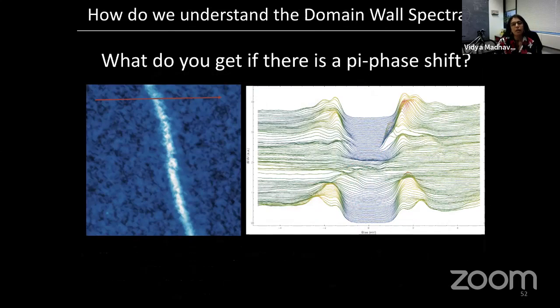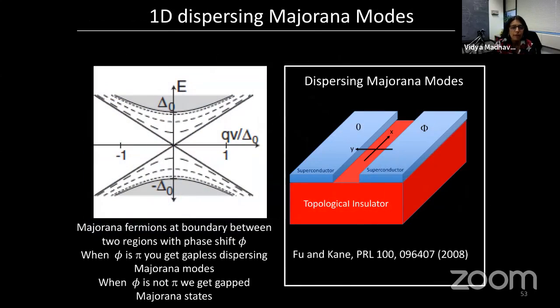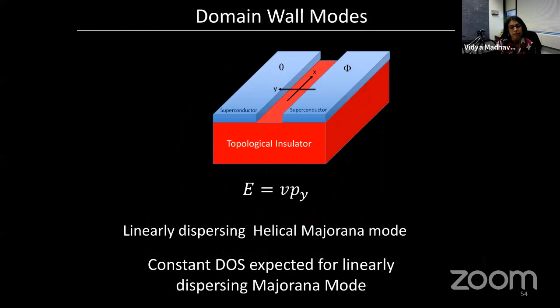To answer that, you can ask, what do you get if there is a pi phase shift? Fu and Kane did this and showed what you expect to see. This is the superconducting gap, which is shaded. Inside the superconducting gap, you should see helical Majorana states. These are propagating Majorana states, which means that along the domain wall, the dispersion looks like this. It's linear. You should see linear dispersion for these Majorana fermions, and across this region, they should be trapped, right at the domain wall.